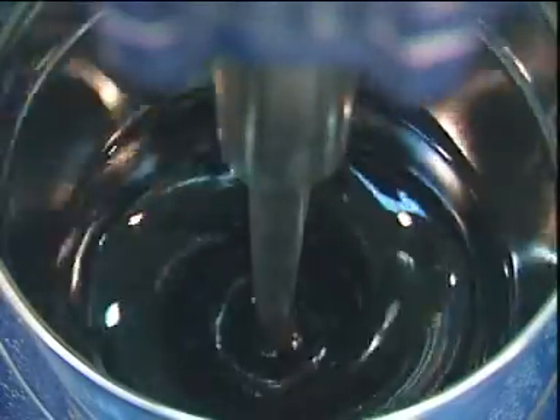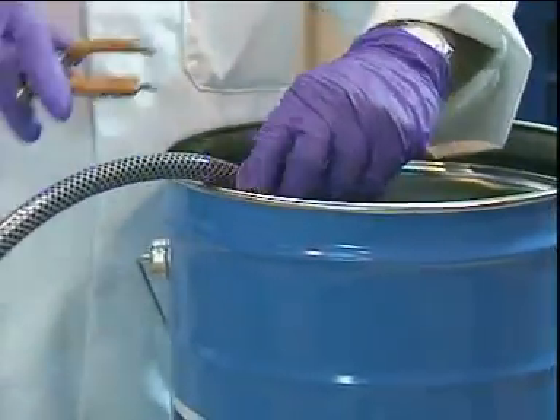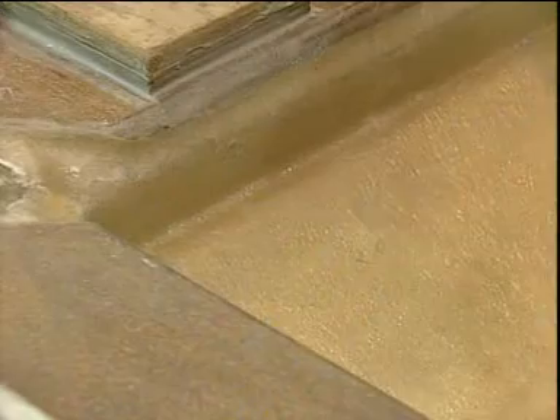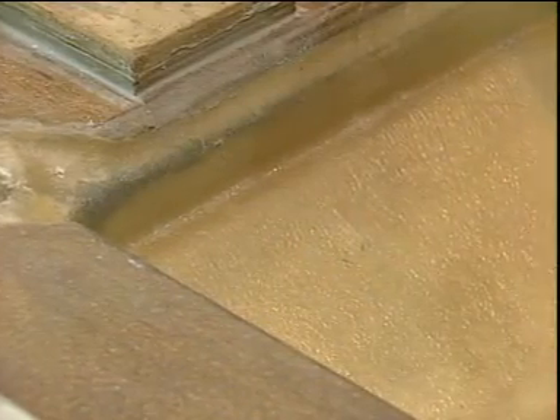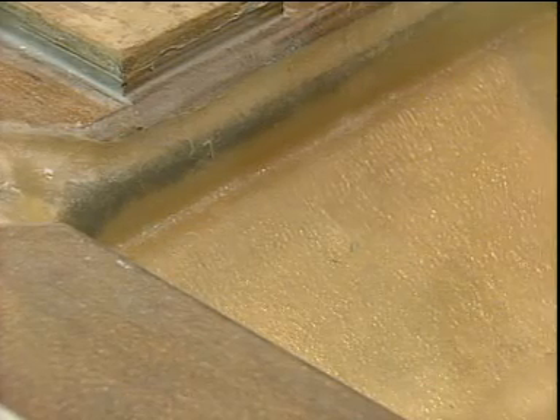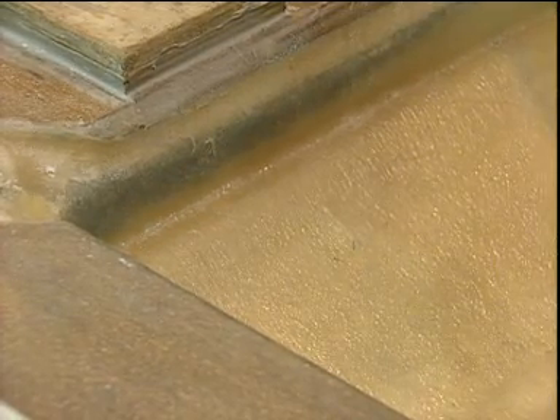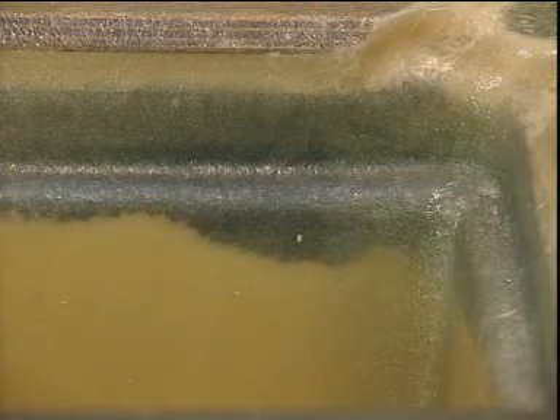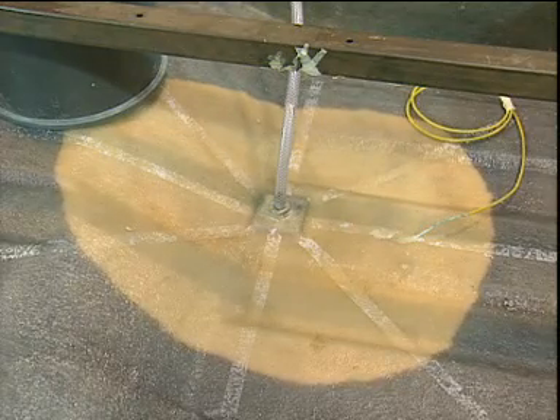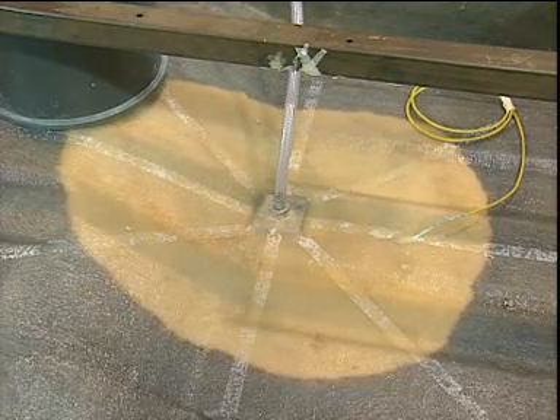The resin is then catalyzed and introduced to the mold via the resin inlet tube. The resin travels quickly around the peripheral channel and then starts to flow through the reinforcement. Injection of this component, which has a developed area of 2 square meters, takes between 10 and 15 minutes, depending on choice of resin and reinforcement.